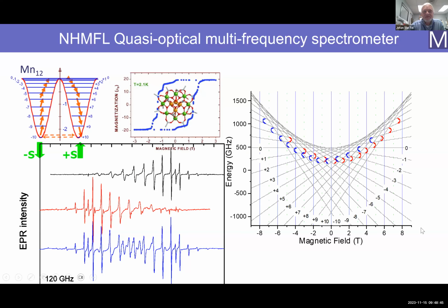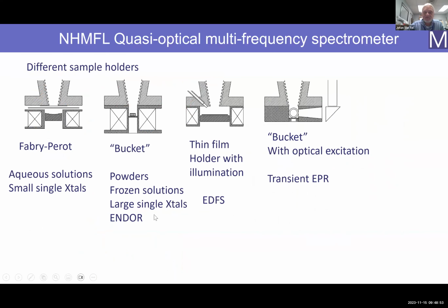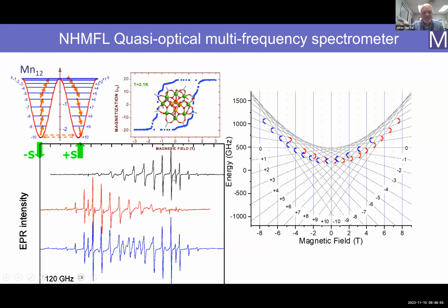So using a right circular polarization or a left circular polarization, you can get different spectra. And the reason is that some of these transitions are left circularly polarized and some of these transitions are right circularly polarized. So if you use just the typical linear polarization induction mode, you get a spectrum like this. But using circular polarization, you can actually select out the different signals with the different polarizations, which is kind of interesting.